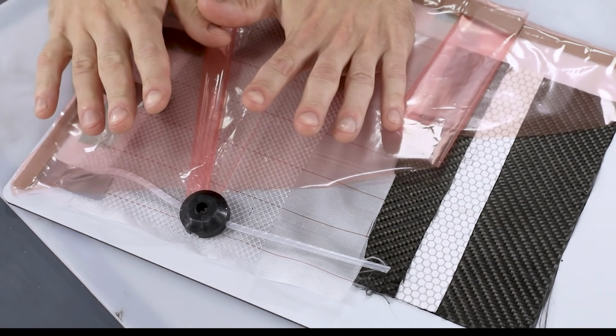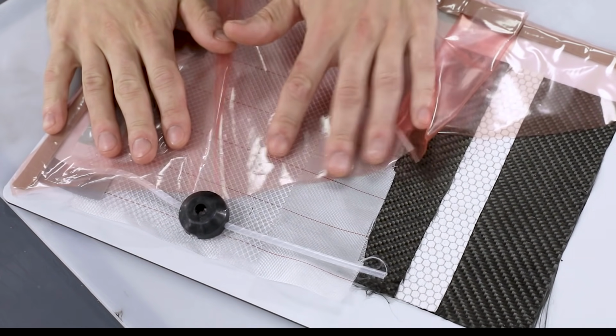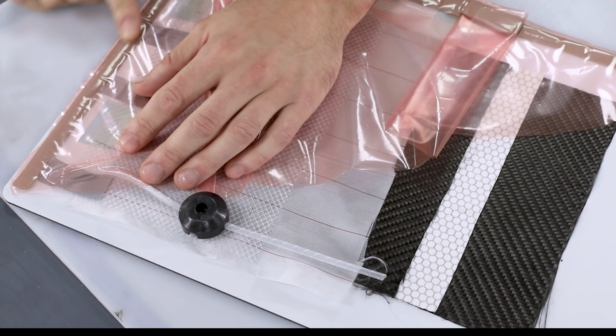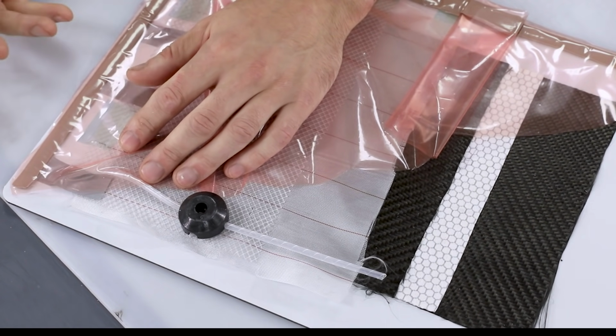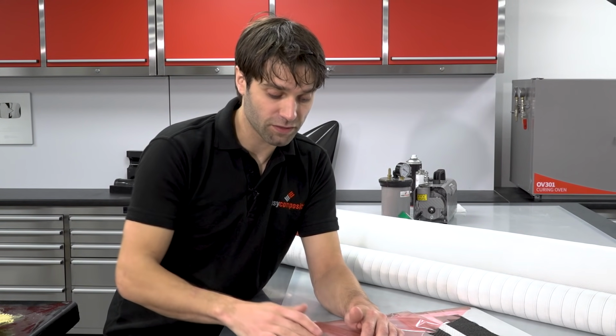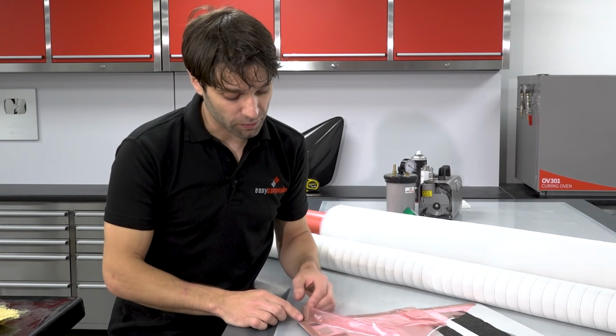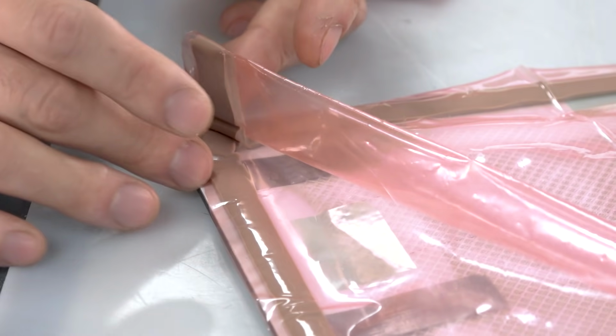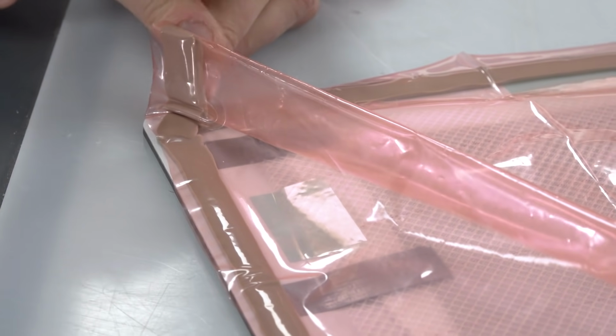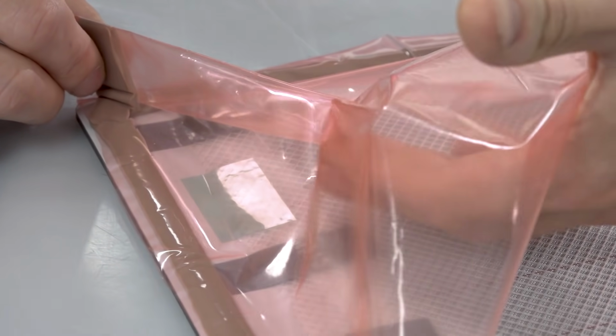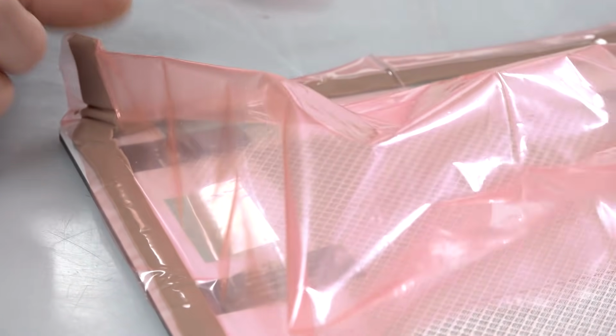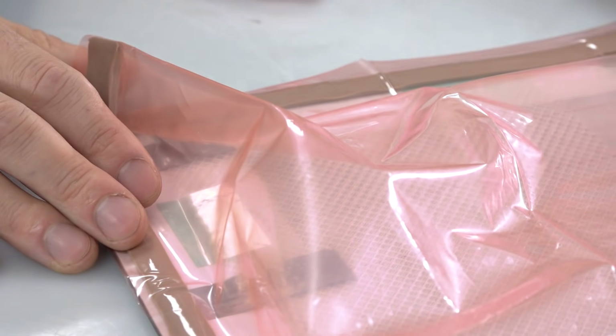Then we have a conventional vacuum bag over the top of that, and then that is sealed to the perimeter or the flange of the mould. Now with resin infusion, 9 times out of 10, you will be sealing to the flange of the mould. So unless you're working with a completely flat surface, you'll also have to include pleats. Now this is where the bag comes up and goes over, and it just gives you that excess bag, which will mean that the bag can follow all of the contours in your moulding without having to bridge or stretch.